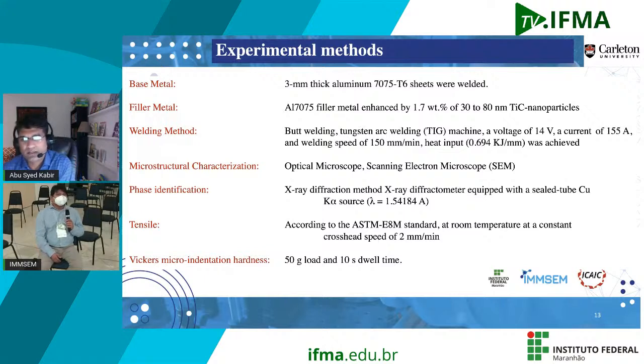Well, speaking about the heat input, we intentionally choose this high heat input because we know the fundamental is that if you have the high heat input, then you actually accelerate the solidification cracks. So we intentionally wanted to create more and more solidification cracks in the structure. The problem with that one is not only does it increase the susceptibility to solidification cracking, at the same time, it increases the porosity as well. The porosity is something we can control with the parameters, but I'll come back to the porosity. Porosity affected our results, that's why I'm mentioning the porosity here.